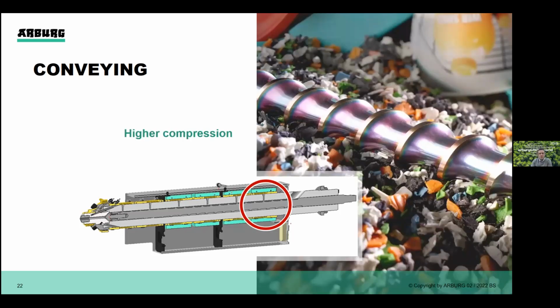But not only modifications to the cylinder geometry can improve the feeding behavior; the screw geometry itself also has an important role in this matter. So what does it mean? A screw with an increased compression is suitable for processing such regrind or recycling material, and therefore we recommend a so-called high compression screw. Based on our experience, this ensures improved melting, but also improved feeding behavior, thanks to its deeper cut feed zone in the screw itself. So this is really a topic of the different shapes and design of the screw itself.